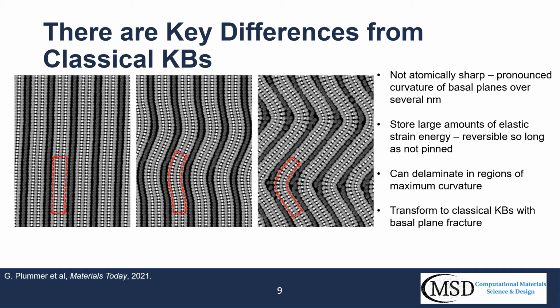This creates quite a compelling explanation for the extraordinary mechanical damping properties displayed by MAX phases, with these tightly coiled layers almost acting as mini springs. We also note that these curved boundaries tend to delaminate in regions of maximum curvature and can transform to something closer to classical kink boundaries when the basal planes do finally fracture.